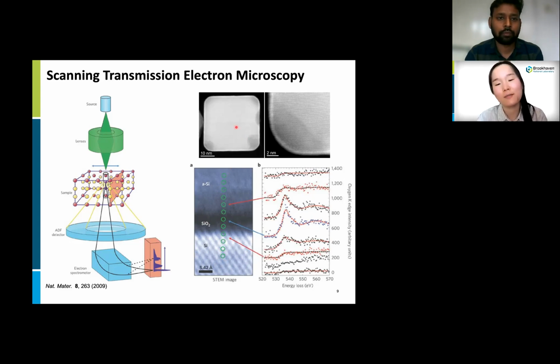From this image, you may see that the edge of the tube sample is a bit brighter than the inner area, because the surface is composed of atoms having higher atomic number.